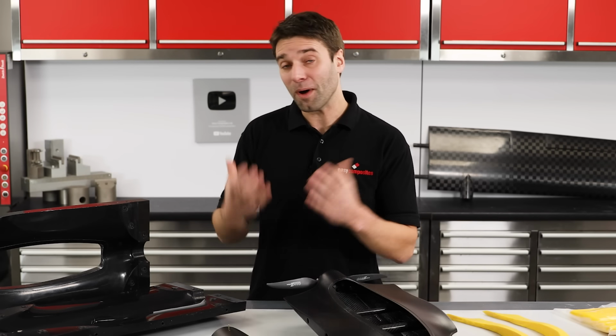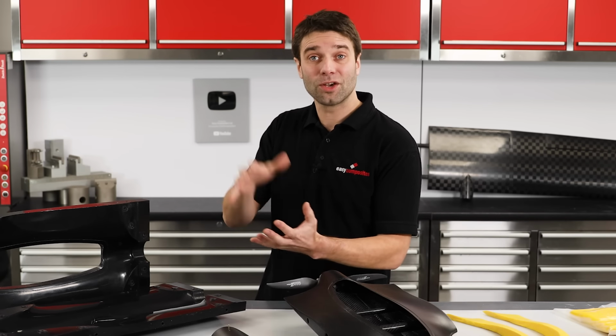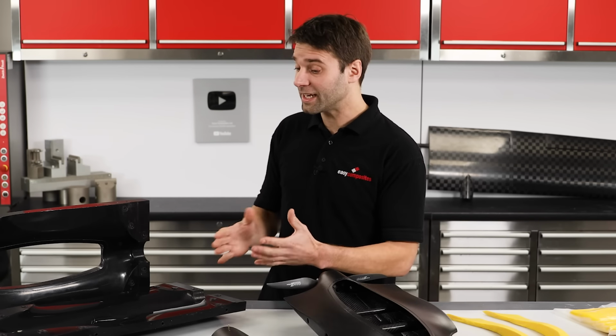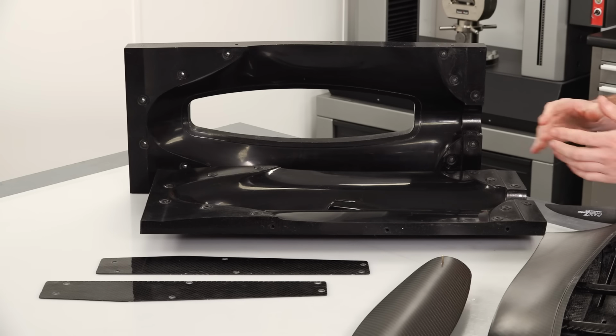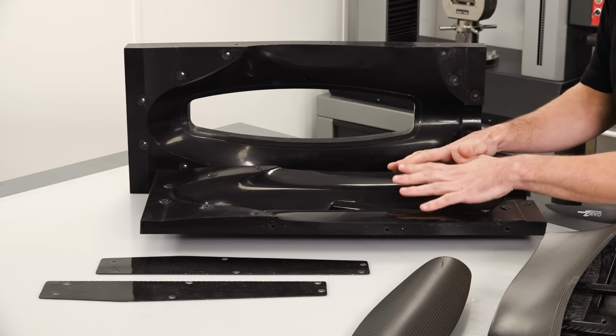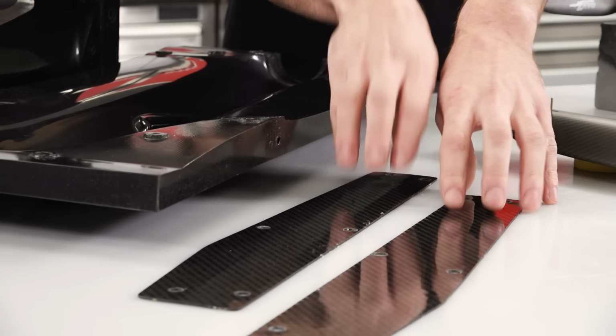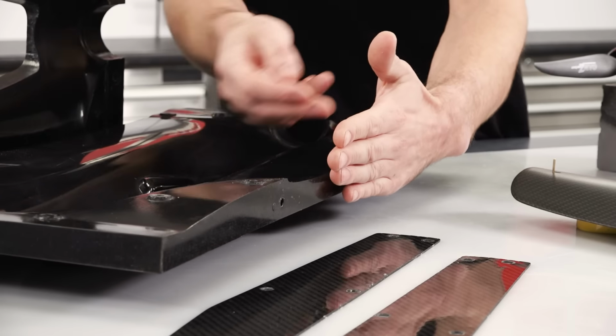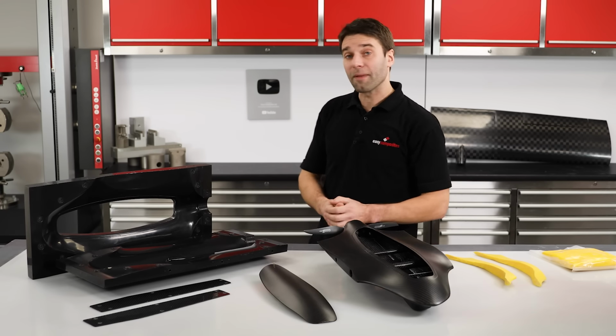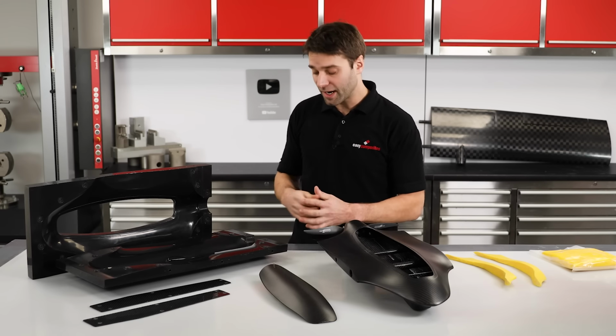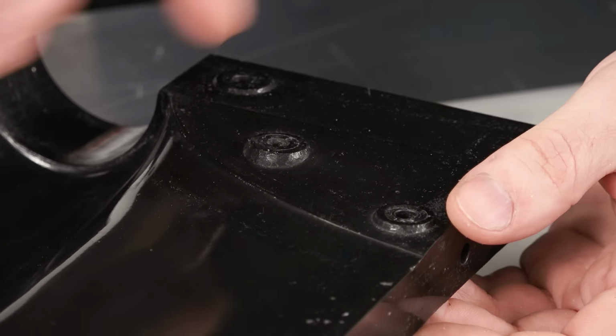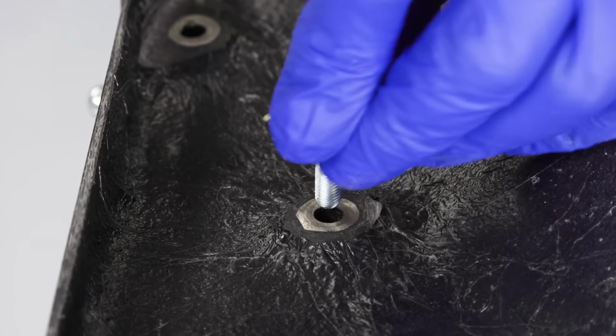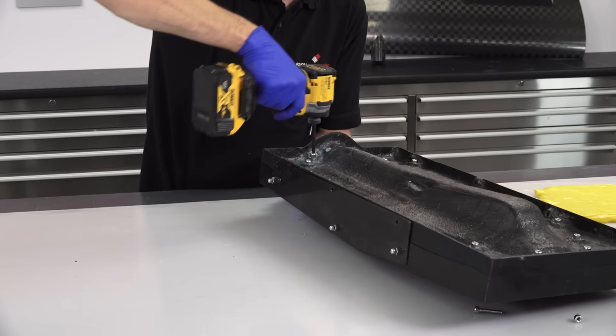The starting point for anything like this will be the moulds, and in the case of a hollow part, you will need a mould that will split into 2 or more pieces. In this case, we actually have a 4-piece mould, so we've got the main upper and lower sections of the mould, then we've also got some side plates that form the wing roots. The moulds themselves are made from XT135 tooling prepreg and also include metal mould clamping bushes that allow the parts to align and be clamped together.